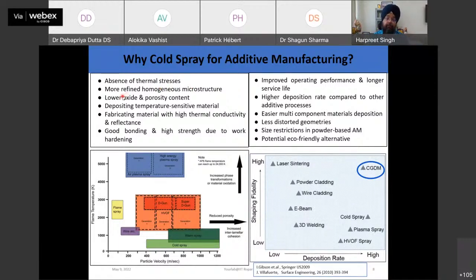Another thing is a more refined homogeneous microstructure. This is another strong point of cold spray. When you do the coating, the particle is coming at a very high velocity, as I said, like Mach number 2 or 3, and it goes through a very small distance. You have already seen the video. In a matter of less than seconds, microseconds, the particle comes and deforms on the surface, and then solidifies on the surface. Now in doing so, you get a very refined microstructure. Here what happens is that you don't have any time for growth, right?